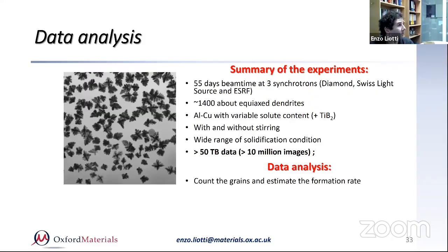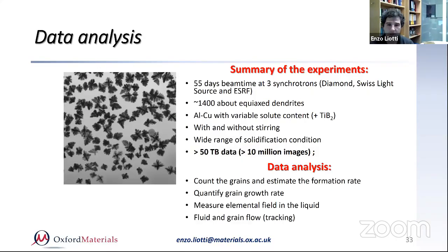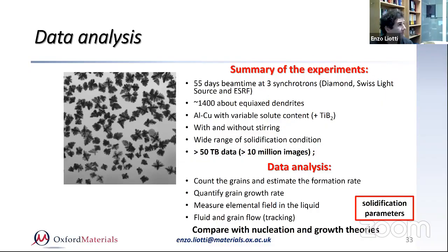So you could actually get a lot of information out of it if you could analyze it. The first thing is, by counting the grain, you could estimate the formation rate and learn about the efficacy or the potency of particles of grain refiner. You could quantify the growth rate if you could measure the elemental field in the liquid, because the experiment allowed us to get a concentration of the solute in the liquid phase, and also get information about fluid and grain flow if you can track the grain.